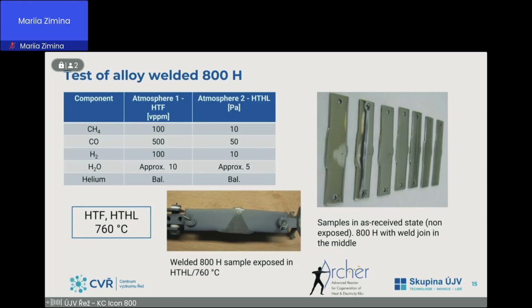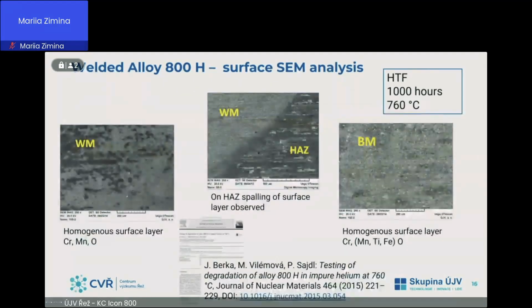So one of the first tested alloys was the welded alloy 800H within the Archer project, with samples containing the weld joint filled with Nicrofer, and the alloy was exposed both in the furnace and the high temperature helium loop. These are pictures of exposed samples in the furnace. The surface layer was relatively compact and homogeneous, but in the heat affected zone, spalling of the surface layer was observed.